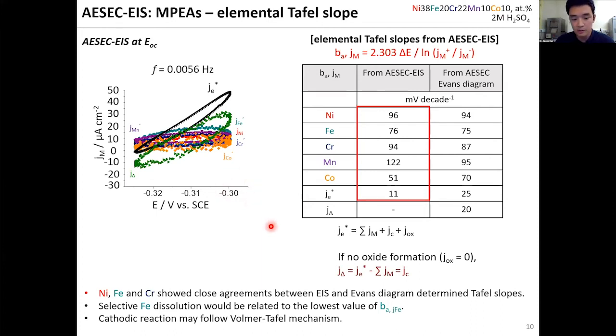So by this, we can see some of the features here. In the case of iron, as reported in other papers using XPS or TOF-SIMS for the same, not exactly the same but similar, elemental composition, it shows selective iron dissolution in sulfuric acid, which could be explained by the lower Tafel slope of the iron.